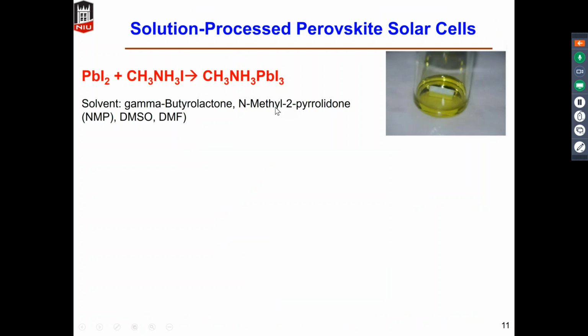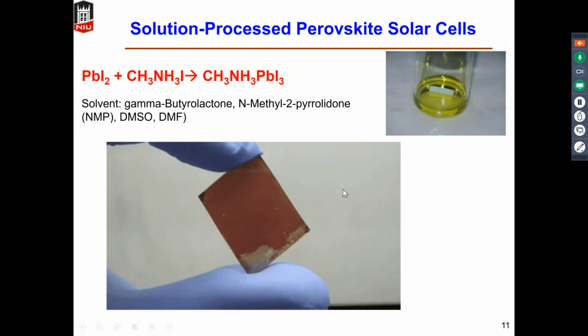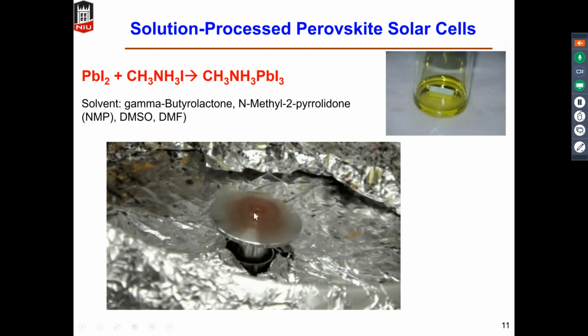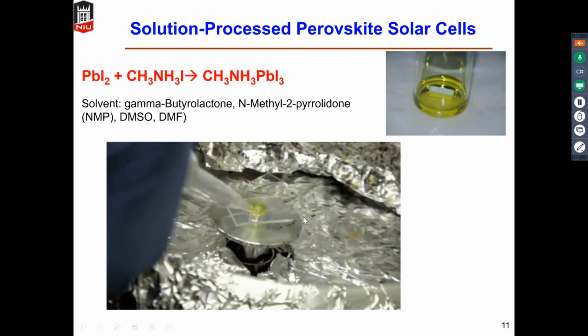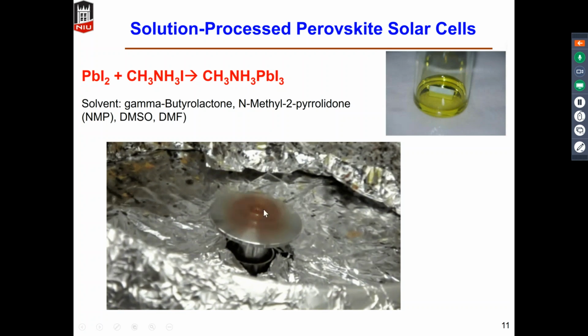The process of making such a film is quite simple. You just dissolve lead iodide and methylammonium iodide in certain organic solvents such as gamma-butyrolactone, NMP, DMSO or DMF. So you get this yellow-greenish solution, and then you just cast it, for example, by spin coater. After the solvent quickly evaporates, you get this dark brown thin film. This is the so-called perovskite thin film. But of course, nowadays there are lots of other thin-film technologies that can coat much better perovskite films, such as blade coating, because spin coating doesn't give you a very uniform film along the radial direction.